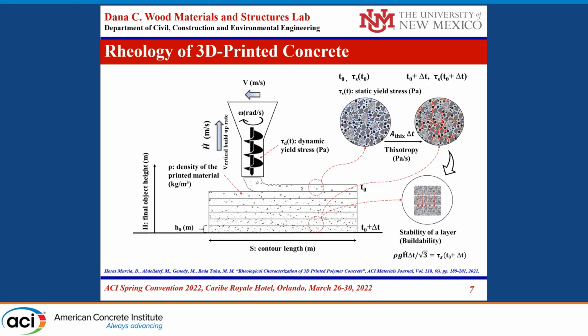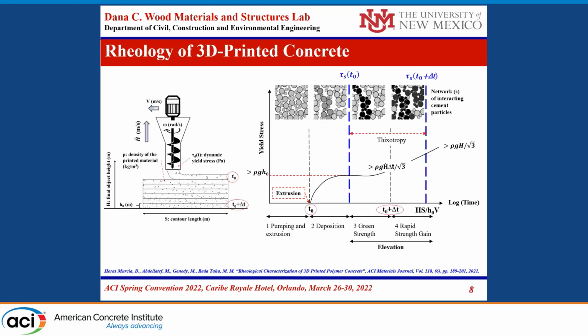As you come to this point in the printing, the layer goes up again, and this affects the stability. And when we look at the stability, this typical equation is only used for the case of strength governing effect, while there are other governing effects other presenters showed, which is the buckling problem, that has become a structural effect during the building of the material. We show here the typical yield stress change of the material because of the change in the weight placed on the material from the different layers, and comparing it to the static yield stress at time T0 and time delta T, and the growth of that stress and the growth of the strength.